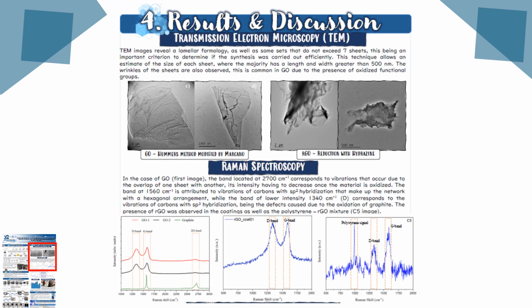Now the results. First we have the TEM image. We can see that both GO and Re-GO have a laminar structure with dimensions larger than a micrometer. However, in the case of Re-GO, we see some sheets that are somewhat damaged or possibly broken, but there are no clusters, no groupings. In Raman spectroscopy, we look for the characteristic signals of both materials.